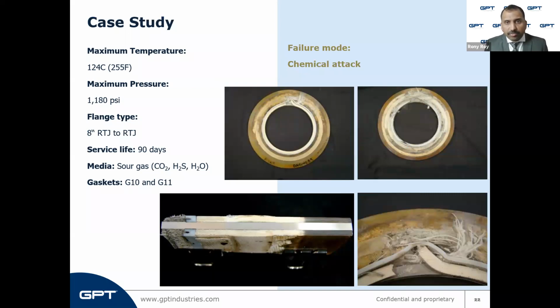The temperature was 124 degrees Celsius, the pressure was 1180 psi, and it was a ring type joint flange, and the gaskets in this were only in service for 90 days. To really get a good understanding of exactly what happened to this gasket, let's have a look at a cutaway view of the gasket in the pictures at the bottom.